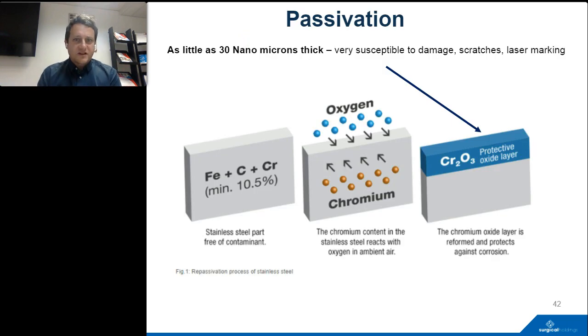And just to touch on passivation, in the alloy itself, stainless steel, the martensitic stainless steel, we have chromium. Chromium does things like make the steel look really nice and shiny, but it also delivers this really vital bit of corrosion resistance, which is the process of passivation. So the chromium in the steel reacts with oxygen, creating a chromium oxide layer, which is formed and protects against corrosion. It's very, very thin, and also quite susceptible to damage and scratching. Laser marking could potentially also damage that if it was particularly deep. So certainly something to bear in mind.